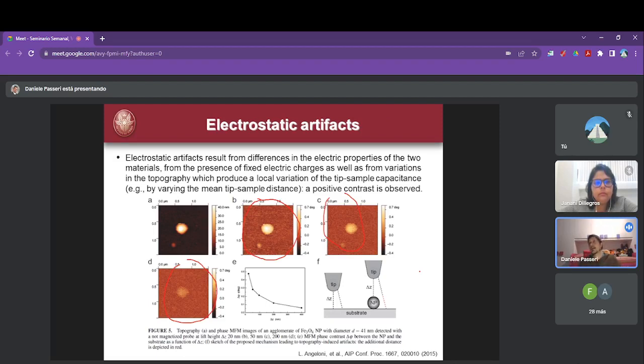Many of them, I can assure you, are fake. They are not magnetic signals. The problem is that there are electrostatic artifacts. Electrostatic artifacts are due to the fact that when you are on a flat substrate, you have this distance between the tip and the sample. But when you are on a nanoparticle, this distance is the same, but the average distance from the sample is bigger. So you have a change in the capacitance.